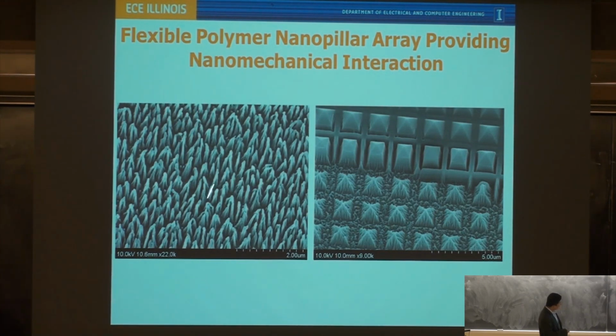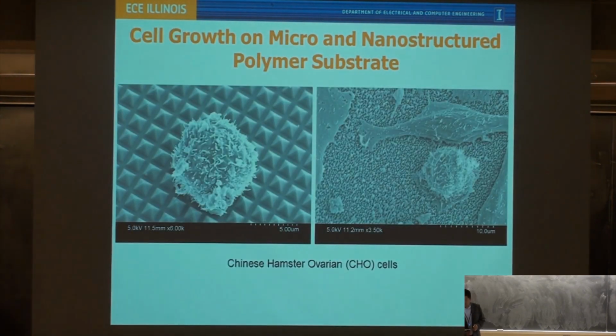We can also make those polymer nanopillars on top of a polymer microstructure. This is a microscale pyramid structure we made out of polymer, and we can make those nanopillars on the surface. Then we use the surface as a nanomechanical interaction tool to study cell mechanics. What we actually observed is very interesting. We tried to culture the cell. This is a CHO cell again. We cultured cells on this microscale pyramid structure and didn't see anything special. But when we started to culture these CHO cells on this nanopillar array substrate, we saw the cells behave very differently compared to their normal behavior.